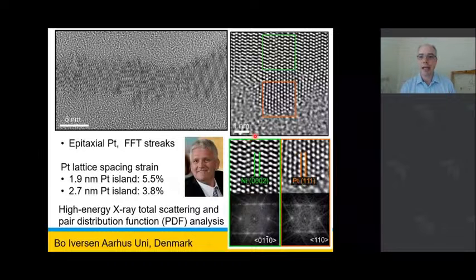So in terms of seeing if we do get the strain that we're after, this is a high resolution image. Hopefully you can see, but this is our nickel here. And if we follow down one of these lines of atoms, you can see that it's a straight line. But when we start getting to the platinum island here, you can see that it starts to bend and distort. And that's the strain that we're seeing visually with the TEM. We can do Fourier transforms of these images as well, and all this streaking is due to the strain of the islands.